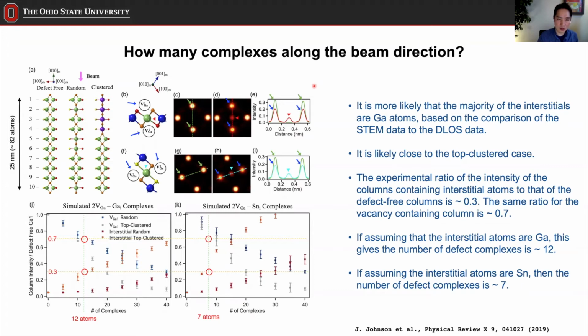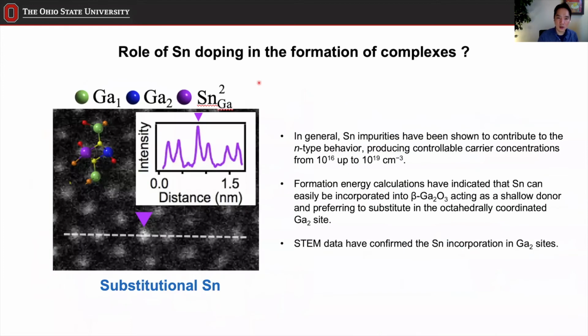Because this is heavily tin doped, it's certainly possible that these cations are tin. Speaking of tin, the theory has provided the likelihood of this tin atom being the most stable at this position right here, which is the octahedral position, and that was also observed in some of our experimental samples, as you can see here. Right here, you have higher intensity. This is the profile. As you can see, the profile has higher intensity, and that is because the tin atom here is heavier than gallium, and therefore the intensity comes out to be higher. So in some cases, we can actually detect them. We have only one proof of that, but we do have confirmation that tin can go to the octahedral site.